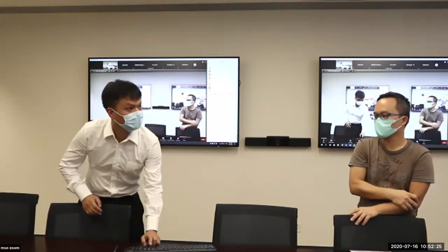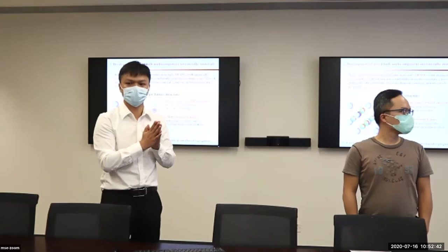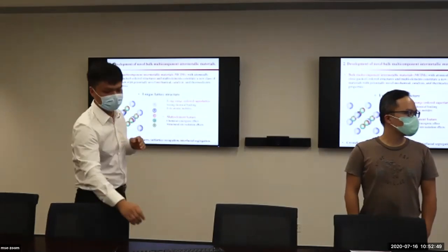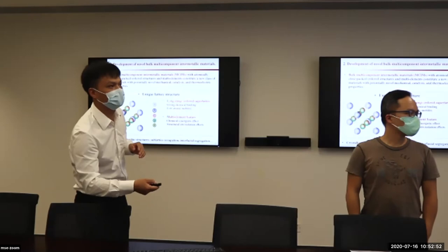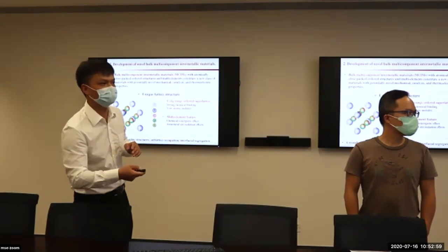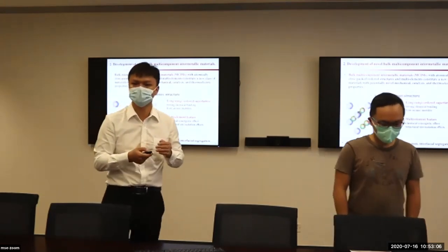The starting point is actually based on the physical metallurgy of the nickel-based superalloy. It's a very typical L1-2 phase. So actually, if I want to design the multi-component L1-2 structure, I will mainly focus on the sublattice occupation behavior. Especially different kinds of elements, when we put these elements into this kind of sublattice structure, the atoms will go into different sites. And when they go into different sites, it will cause changes of the properties in different aspects.